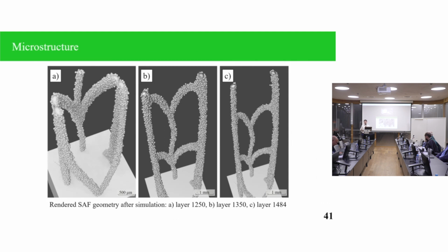If we can make such a multi-layer simulation, which is actually not often performed in literature, we can even try to take the data file from our machine, where we have all the vectors for laser movement, and take this information to our software. So the laser beam, the heat source during the simulation, moved as in the experimental setup. And we just tried to perform this simulation of many layers. And this was not for optimization techniques.